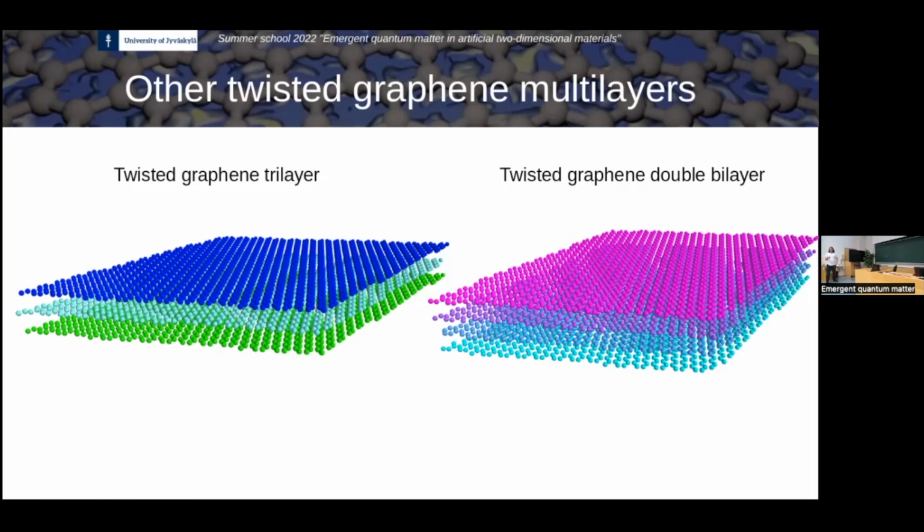So if you think in terms of electric fields, in this twisted double bilayer you are going to have a built-in electric field for these 2 layers in the up direction and for the other 2 layers in the down direction. The structure itself creates an electric field in the double bilayer. And if you think in terms of the topological properties of a biased bilayer, this means that the structure itself is opening up a topological gap in twisted double bilayer graphene, just from an intrinsic built-in electric field coming from single particle physics.